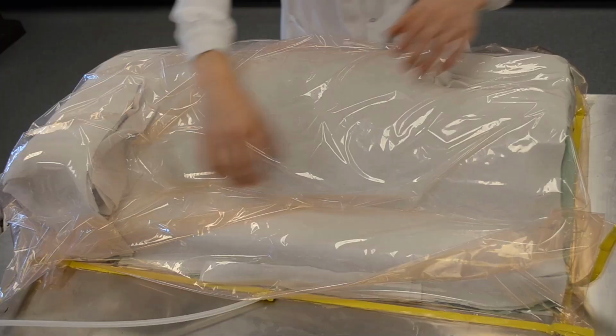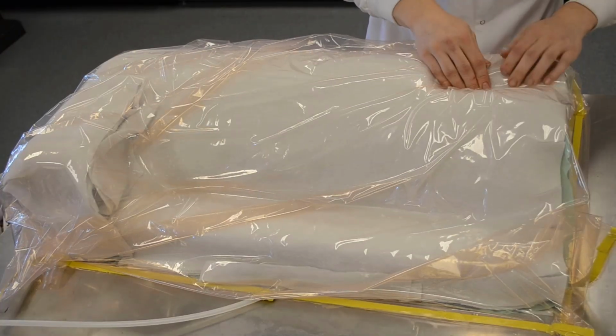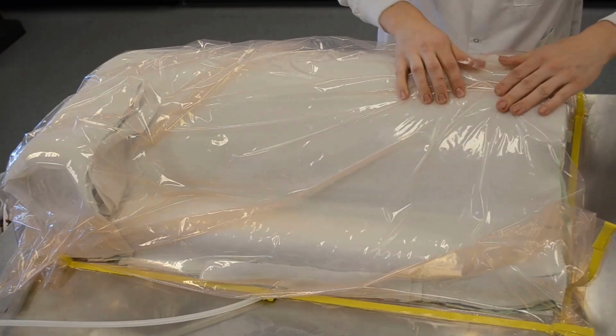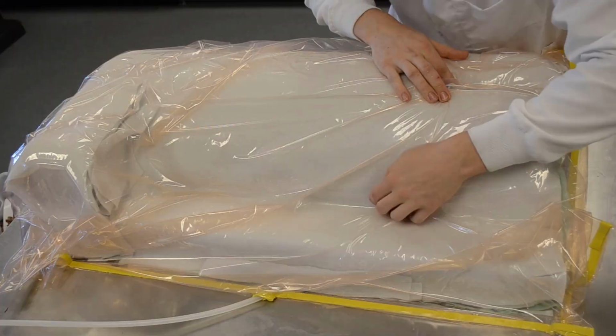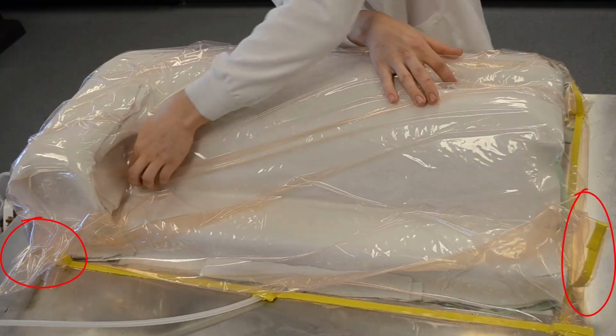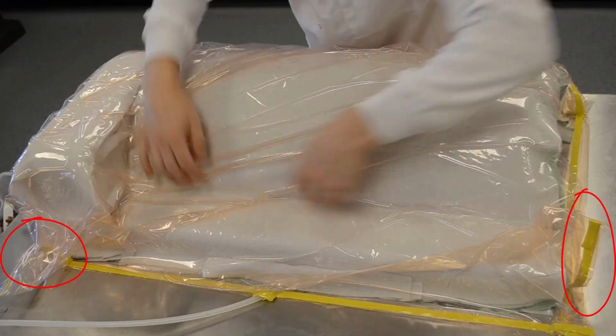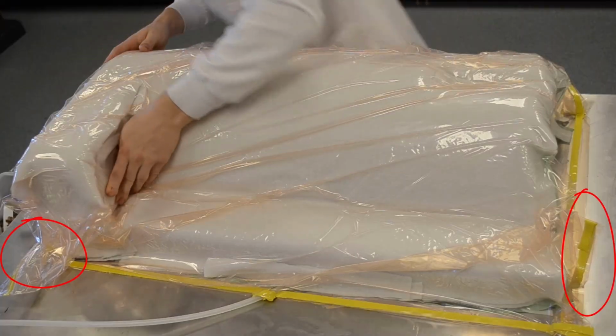and the lack of additional permeable material can reduce the volume of resin removed from the part and reduce fiber volume fraction. As vacuum is pulled, we can double check that all inside corners are not bridging and the fabric and consumables are held tightly against the mold. We included loops of extra vacuum bagging material, called pleats, around the edges to ensure that there is enough vacuum bag to reach into all contours of the tool.